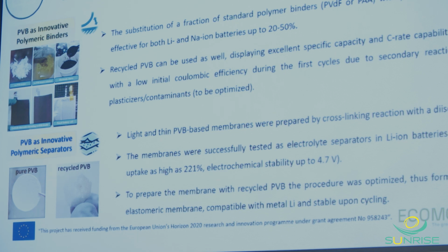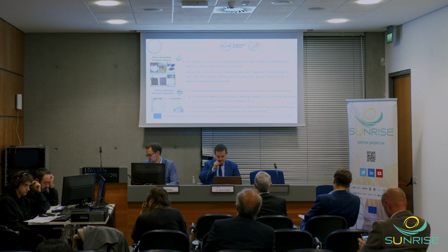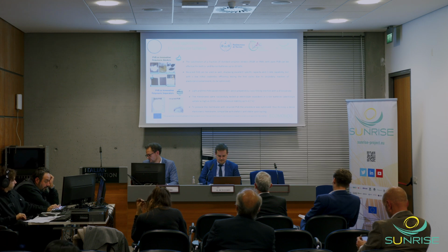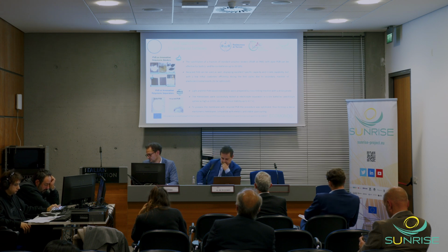Finally, the last application we have been working on is PVB as binder and polymer material for separators in batteries. Here we have been working with mixtures, in the case of binder, substituting PVDF at 20% to 50% concentration, and there have been good results with the 20%. There is no detriment in the binder functionality. And also for polymeric separators, there have been good results using membranes. This probably could be limited for some types of voltage windows, but there have also been good results using PVB as separator here.